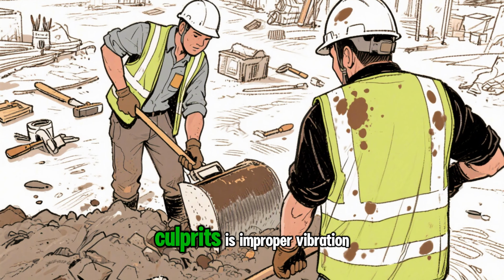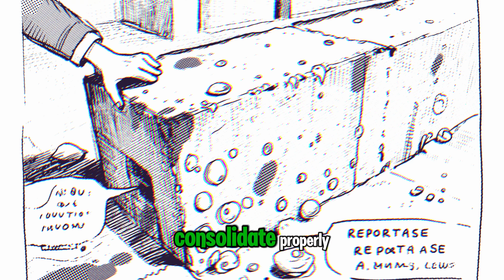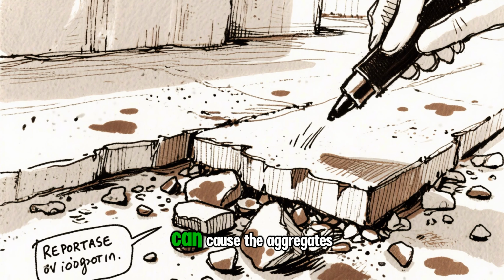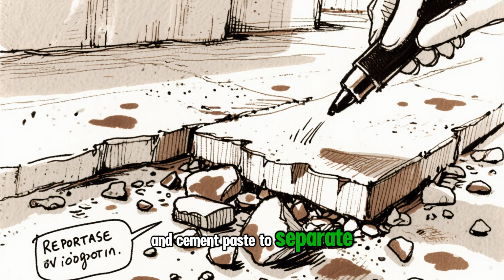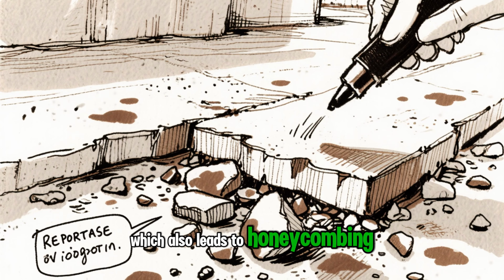One of the biggest culprits is improper vibration. If the concrete isn't vibrated enough, air gets trapped, and the mix doesn't consolidate properly, leaving voids. On the other hand, over-vibrating can cause the aggregates and cement paste to separate, which also leads to honeycombing.